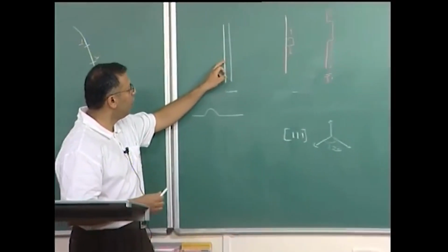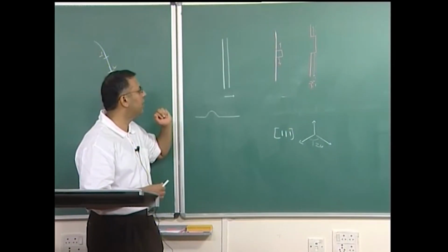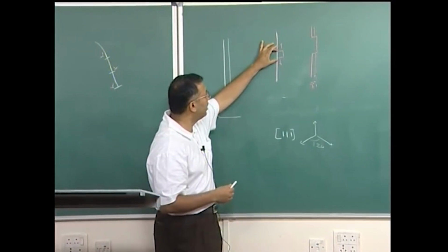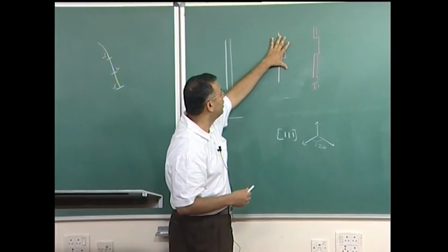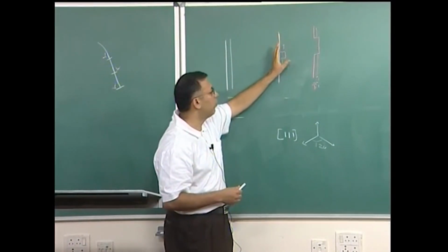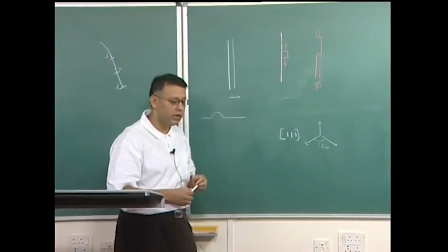So, this is the analogy given to understand how a dislocation weakens a crystal, but this is a second order effect, wherein even this whole dislocation need not go by one single Burgers vector, but you can nucleate a kink pair, and this kink pair can propagate orthogonal to the direction of the motion of the dislocation, finally moving the dislocation. So, I can have a second order mechanism operating, which is going to weaken my crystal.